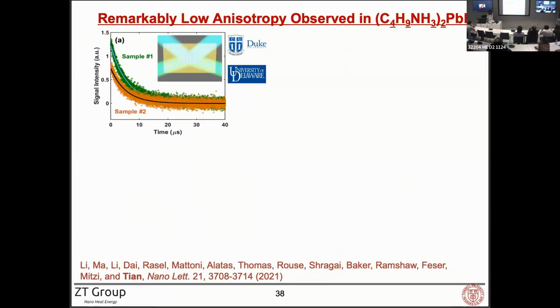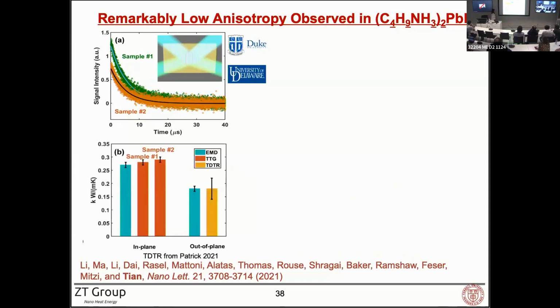So when we did the measurement on the 2 sets of samples, we got pretty much the same thermal conductivity for the in-plane direction. It's about 0.28, 0.29. We did a molecular dynamics simulation. We got pretty much a good agreement for the in-plane direction. And we took the thermal conductivity data from Patrick Hopkins' group and also compared with our molecular dynamics simulation results. They agree pretty well with each other.